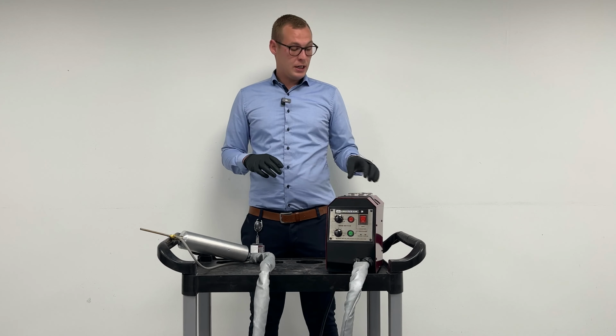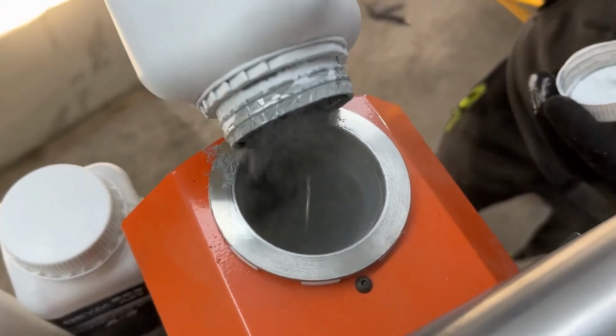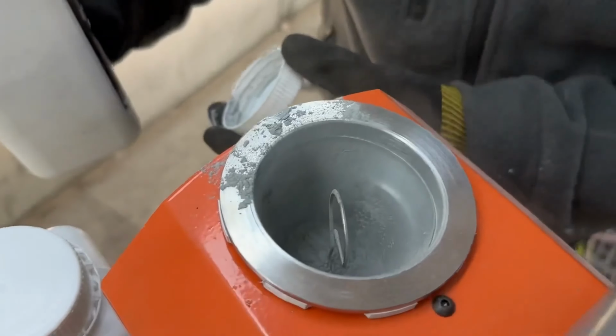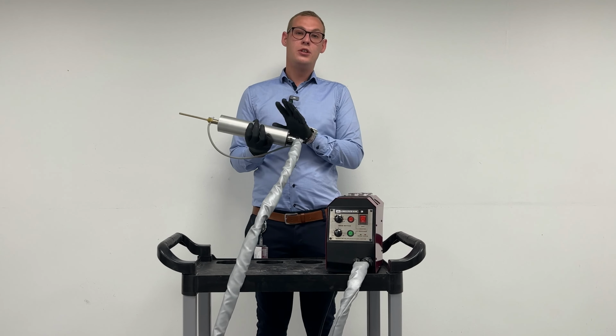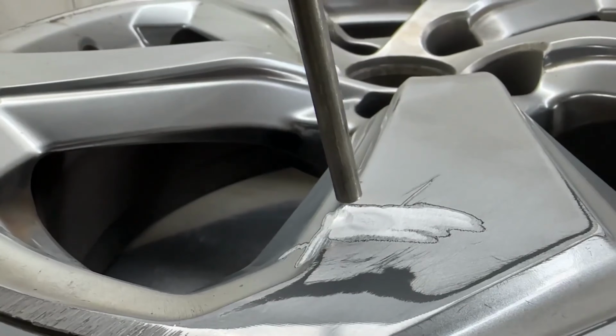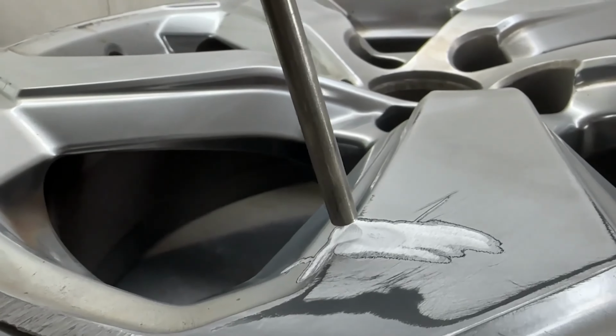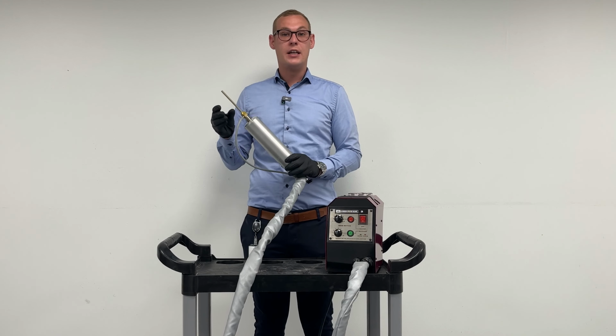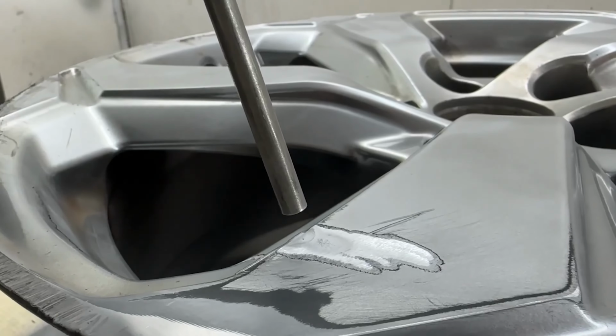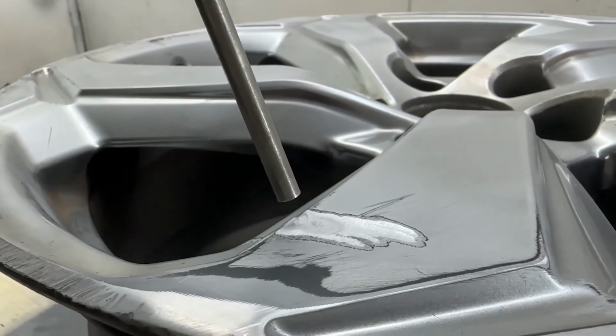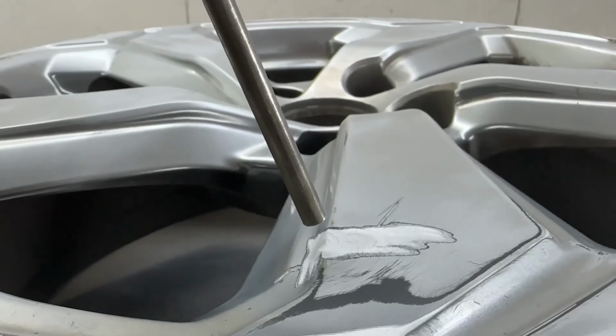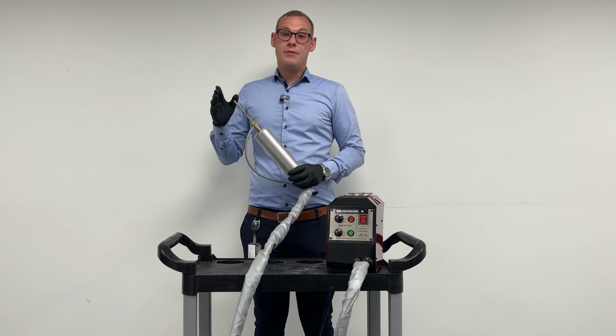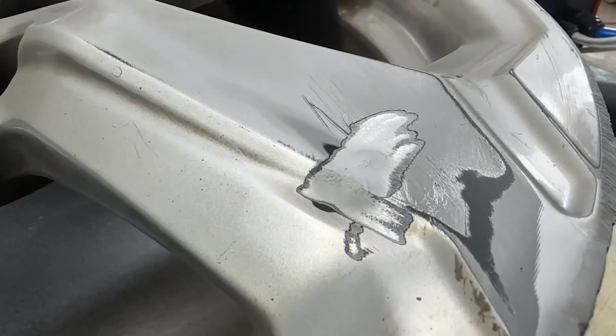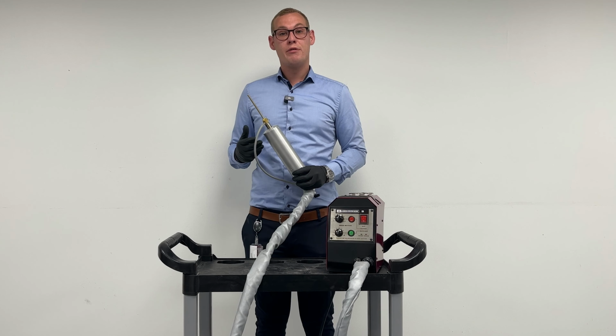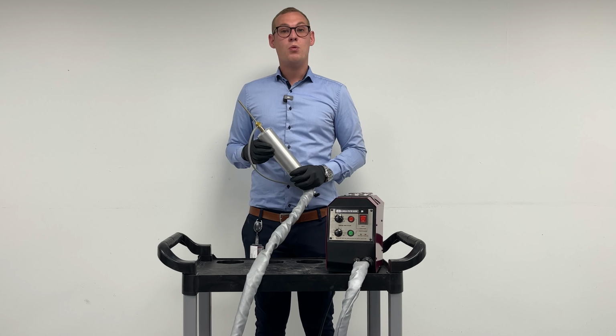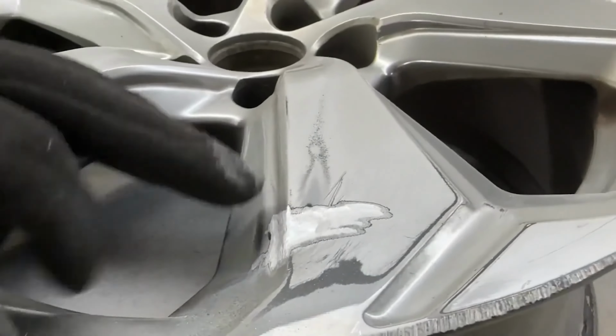The way that the machine works is that you fill in the aluminum in the container here. Then it takes the aluminum through the feeding hoses and into the heating element. In the heating element, the aluminum powder basically gets heated up to 400 degrees and gets liquefied, that can then be shot out of the nozzle here. And then once it reaches the surface, the aluminum is bonded with the surface. The way that it works is that the aluminum, when it hits the surface, doesn't surpass 50 degrees. This means that it's safe for aluminum, so it doesn't crack when you add the aluminum to the surface.